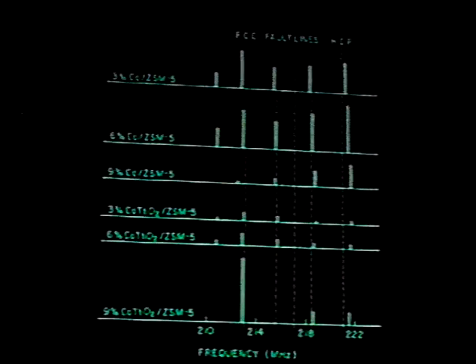Now, our original aim was to look at shifts in cobalt frequency because of thoria addition, but it turned out that the line widths were about 0.3 megacycles, and we could not really tell whether there was a shift in the NMR frequency of cobalt because of the addition of thoria.